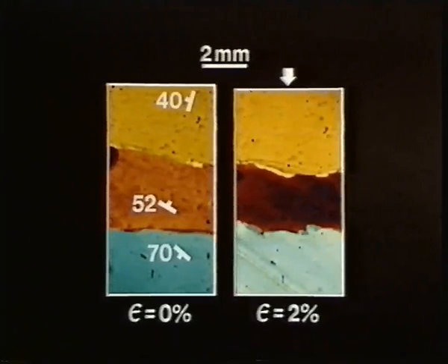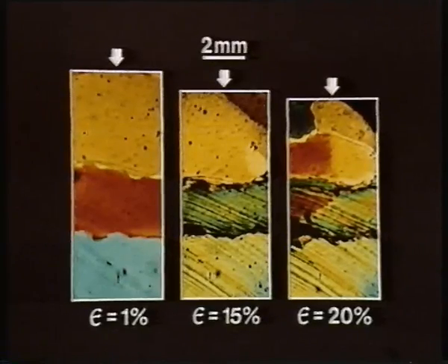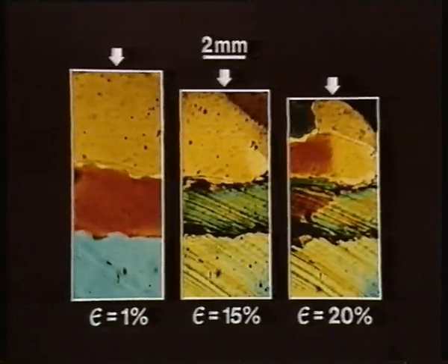After the sample has been subjected to a pure shear involving a shortening of 2%, the blue and brown grains exhibit the development of slip bands, which are produced as a result of glide on their basal planes. Accompanying the glide, there are also minor grain boundary adjustments. The blue and brown grains are also the first grains to undergo an obvious change in crystallographic orientation. This can be seen in the marked change of their birefringence colours to the yellow-green colour observable at higher strains.